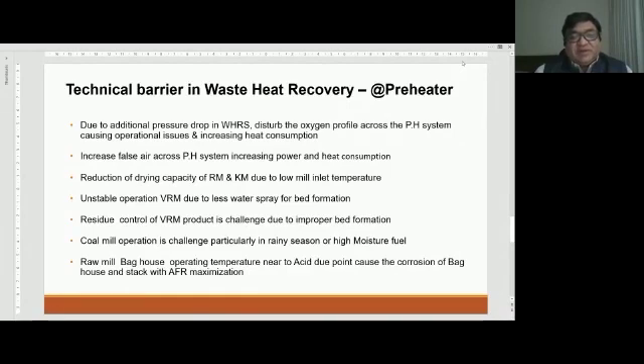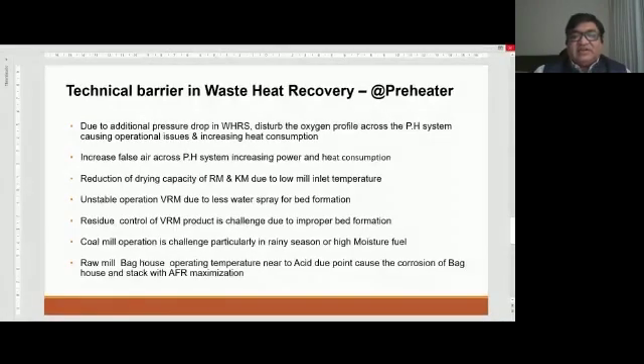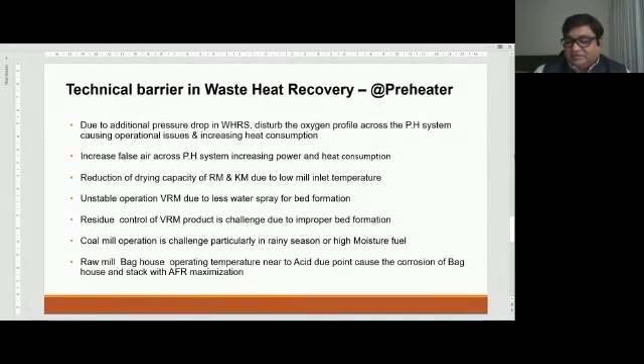So these are the problems we face, the technical barriers in the WHR, especially on the preheater side. Whenever we decide to use WHR, please make sure that these points have been taken care of, and that sufficient heat is given to your drying system, the raw mill system or coal mill system, as well as to maintain your acid dew point in the flue gases, which is a very important part. From my experience, we have to maintain certain dew points, especially in the preheater.